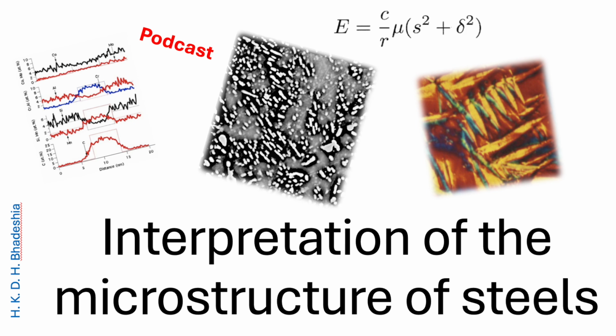This nucleates within the grain, far from any boundary influence, so it's unrestrained, and it develops a perfectly crystallographically faceted shape, like a miniature cube. And what's the big structural giveaway for all of these reconstructive products? Because they are diffusion controlled and atoms are breaking bonds, phases like ferrite or pearlite can actually grow across austenite grain boundaries. They can thicken right into adjacent grains. And that's a huge clue.